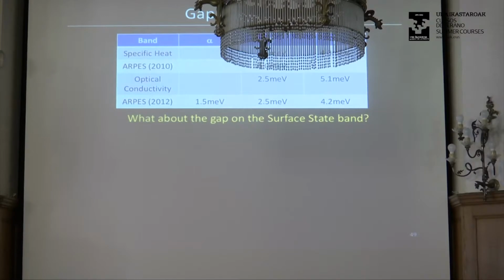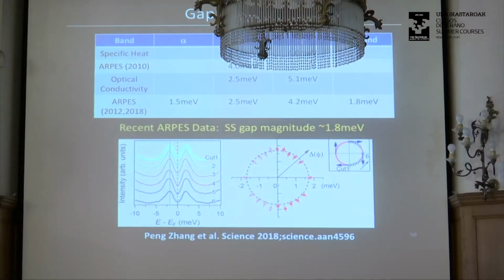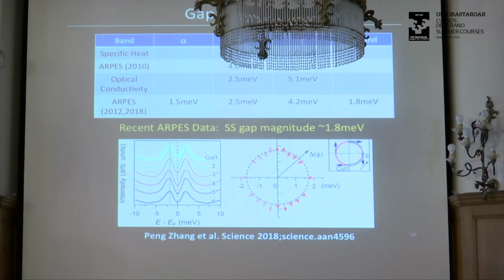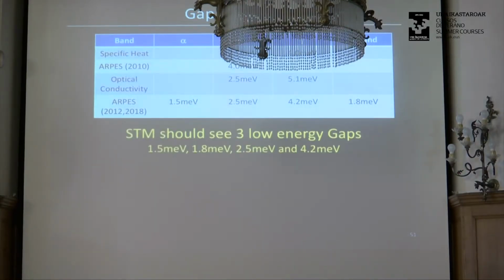Okay? Of course, if you have a surface state, then you should have a gap on the surface state. And in fact, Hongding has measured such a gap, and the claim is that that gap is 1.8 millivolts. So essentially, if you include the surface state gap, leaving aside the 4.2 meV gap, below 3 millivolts you should see 3 gaps: 1.5, 1.8, and 2.5 millivolts. All right? So let's see what STM sees.